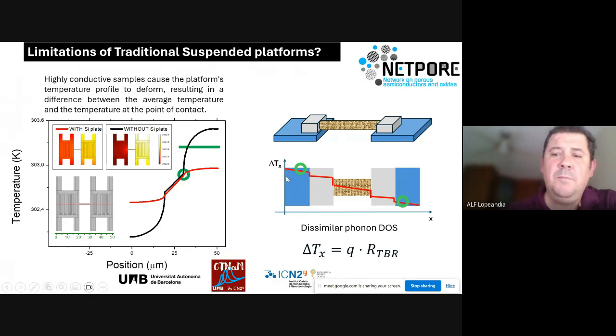But there is a second limitation that has to do with the thermal contact resistance. We have dissimilar materials. We have silicon nitride, we have the nanowire in between, and we make the contact with the metallic polymeric based material, and the heat will flow through the silicon nitride towards the metal, towards the nanowires, and come back, from one side to the other.